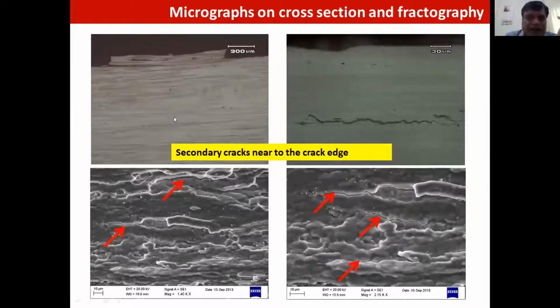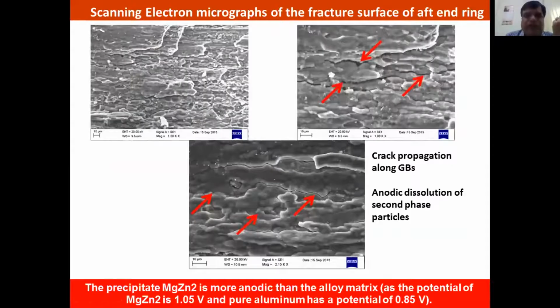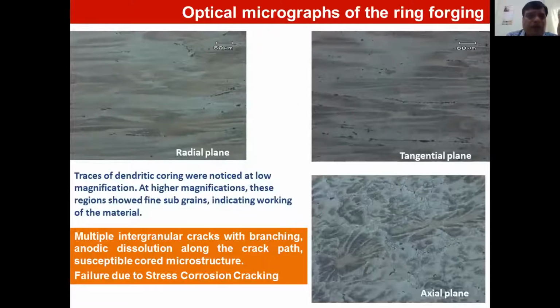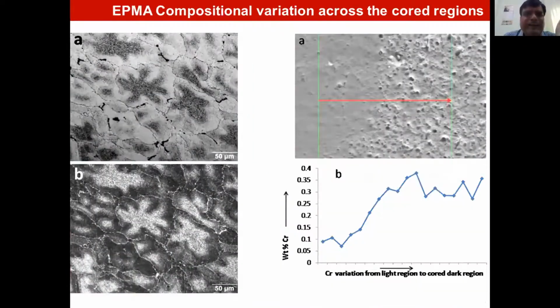And we saw multiple cracks on the fracture surface. You can see secondary cracks near the fracture edge, and in the optical microstructure very near the primary failure edge, you can see multiple cracks running along the main crack. And of course, we are seeing anodic dissolution of the precipitates, which indicates that it has a stress corrosion cracking problem. We saw extensive dendritic coring in the microstructure, because this is a very large size ring. Enough forging reduction could not be given from the cast ingot stage. So you have these flowery patterns in axial, tangential, and radial directions. These kinds of segregation patterns are not desirable in the material, and this being AFNOR 7020, an aluminum zinc magnesium alloy, it is prone to stress corrosion cracking. But we had been using this material, and unfortunately it leaked on the launch pad.